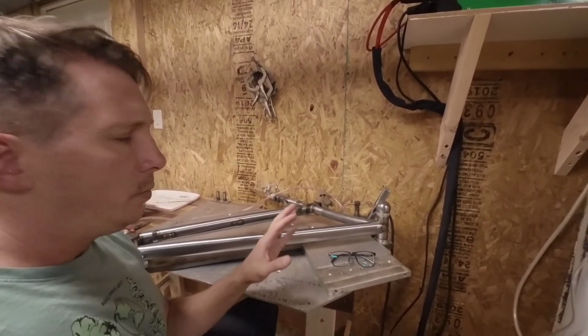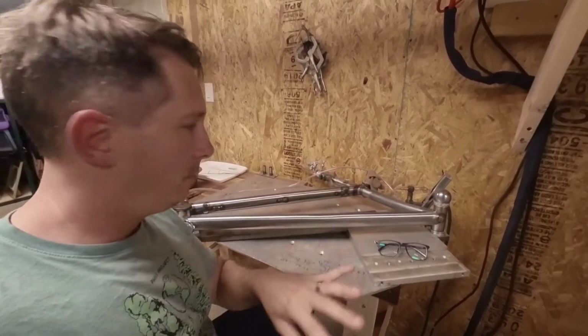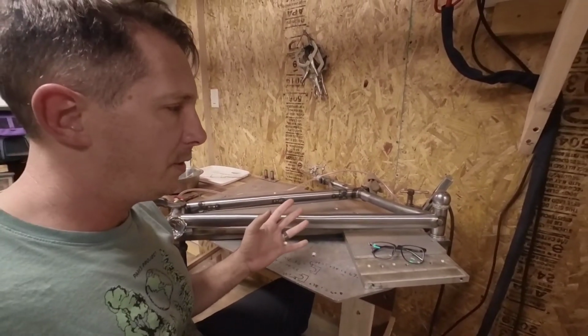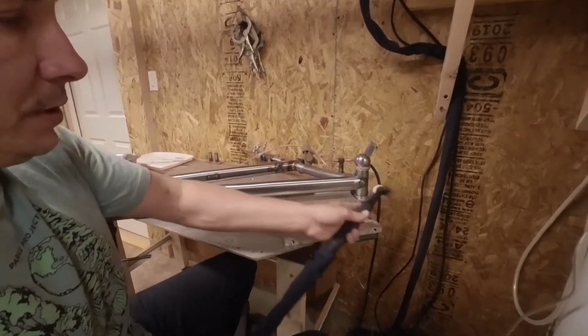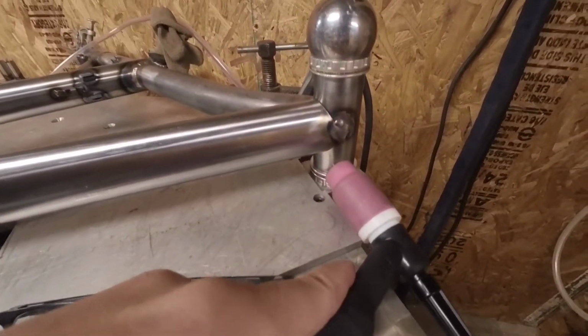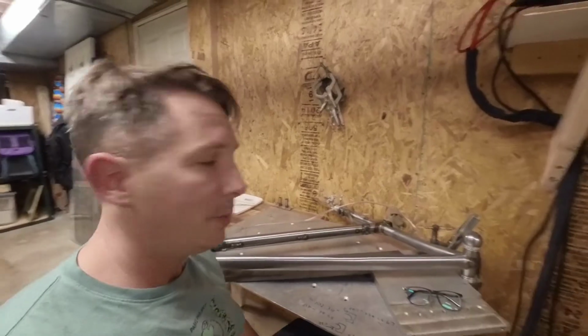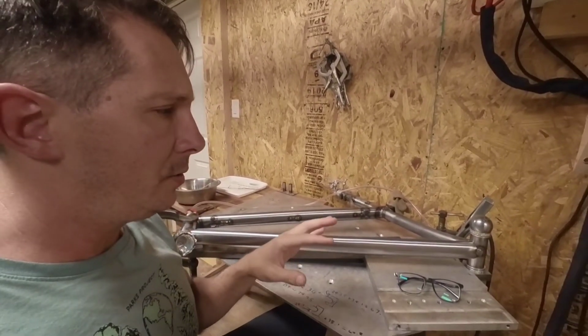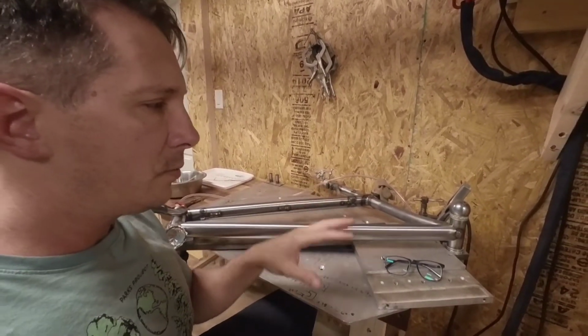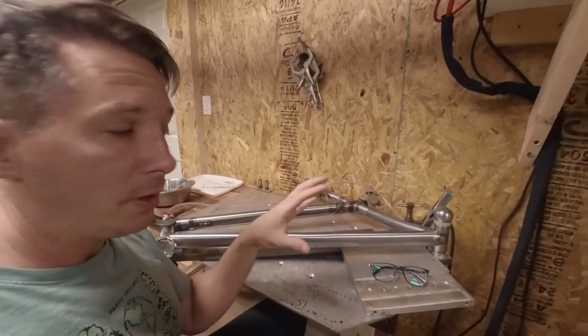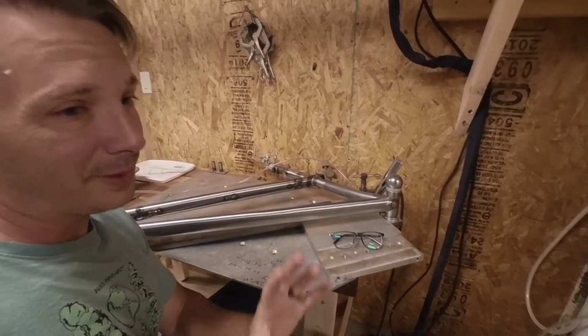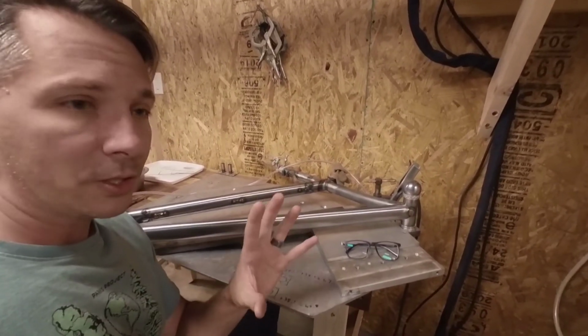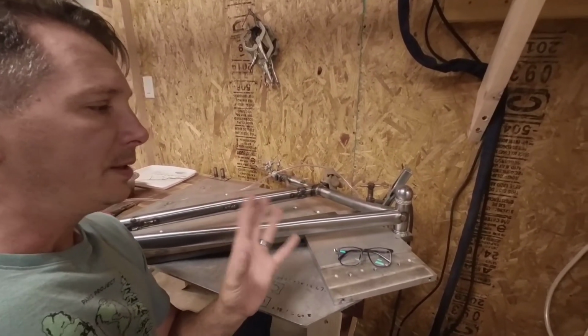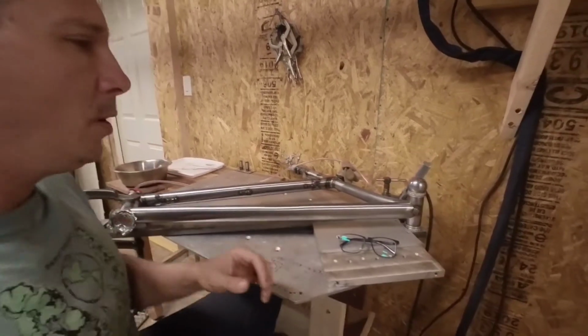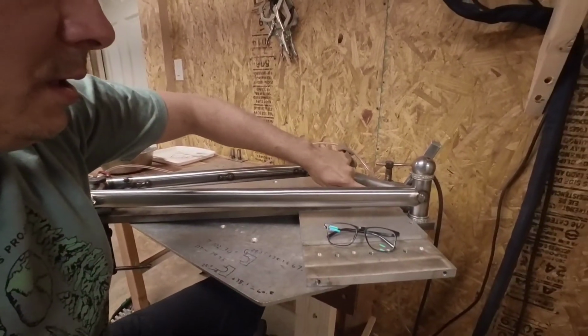In a perfect world, you would weld completely in the fixture, finish all the welding, but the way my fixturing is, it's just impossible to get access to some of the areas. You just can't effectively weld there. So what I do is I do a sequence of welds that I know aren't going to pull the frame out of alignment. I mean, all welds will pull the structure out of alignment a little bit, but the minimum I can possibly achieve. And that mostly means keeping the welds inside the plane of the frame.